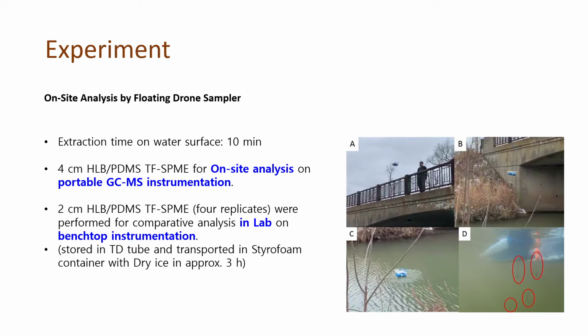The sample for the lab was stored in a TD tube and transported to the lab in a styrofoam container with dry ice in approximately 3 hours. The temperature of the atmosphere at that time was -4 degrees C, and the water temperature was 1 degree C. There was a thin layer of ice on the surface of the water.